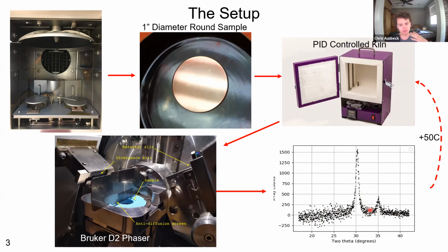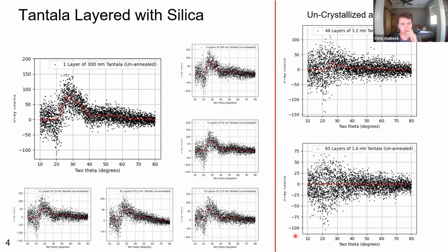After doing this and analyzing our scans, we then increase the temperature by 50C and we redo the process. Starting out with tantalum layered with silica, from one layer of 300 nanometer tantalum, which is our thickest layer, all the way down to 19 layers of 12.5 nanometer tantalum, we see that we have very nice amorphous peaks. And these are all prior to annealing. However, for 48 layers of 3.2 nanometer tantalum, as well as 65 layers of 1.6 nanometer tantalum, we see that these amorphous peaks have either diminished or have disappeared.